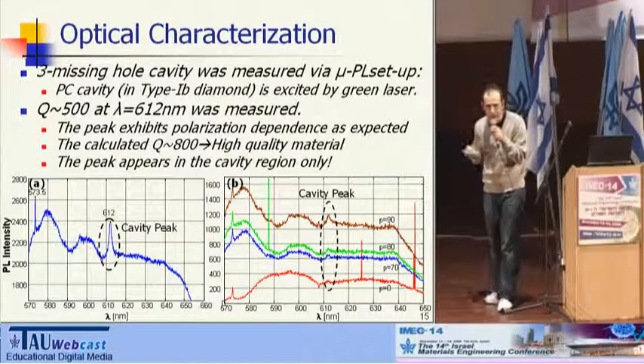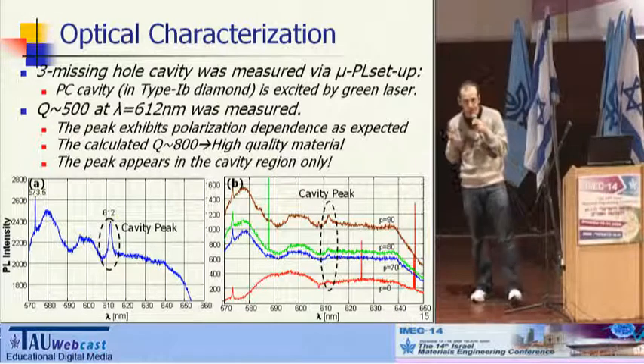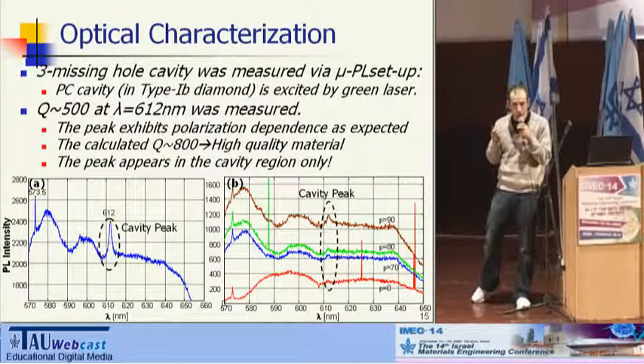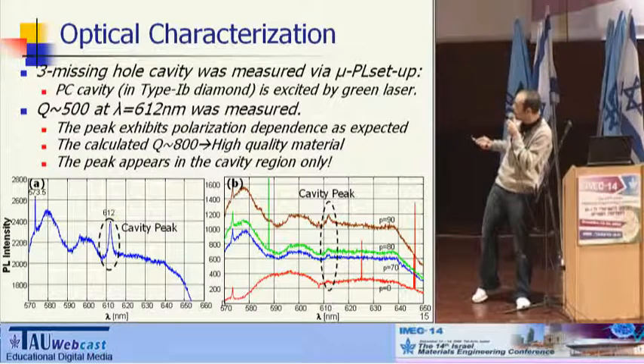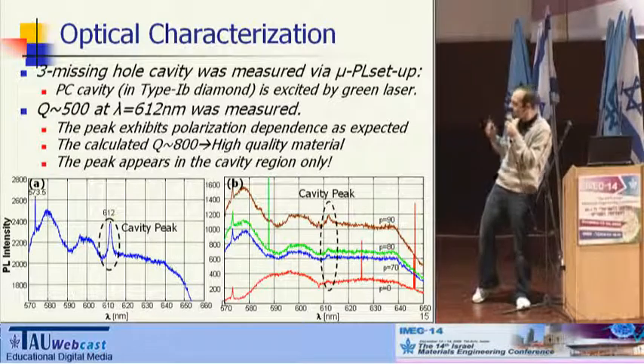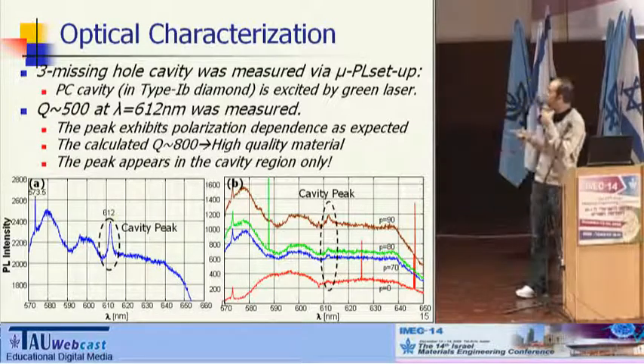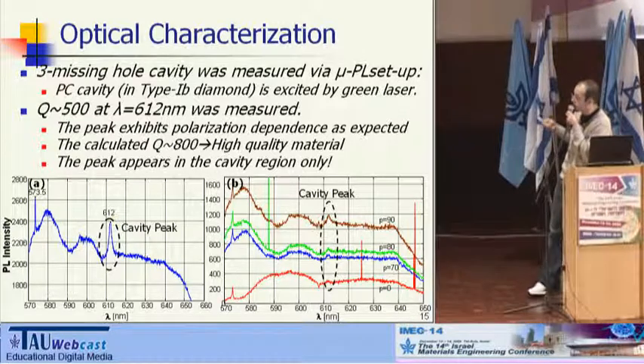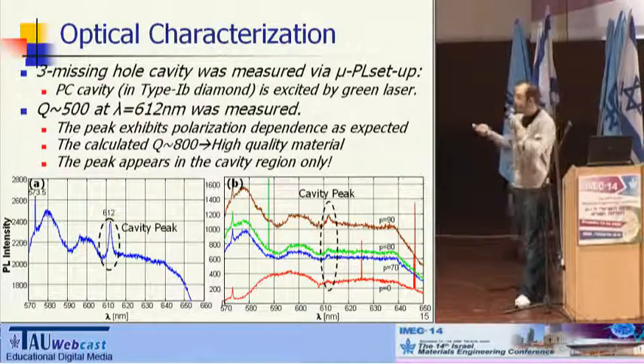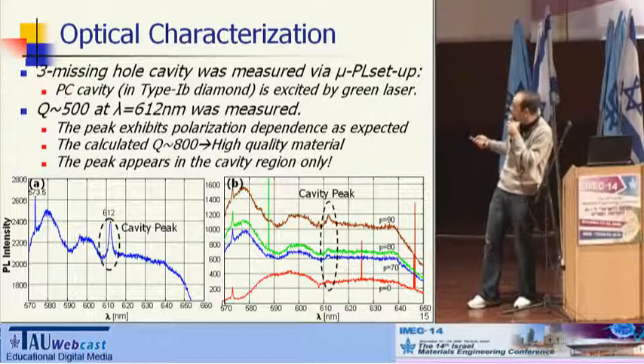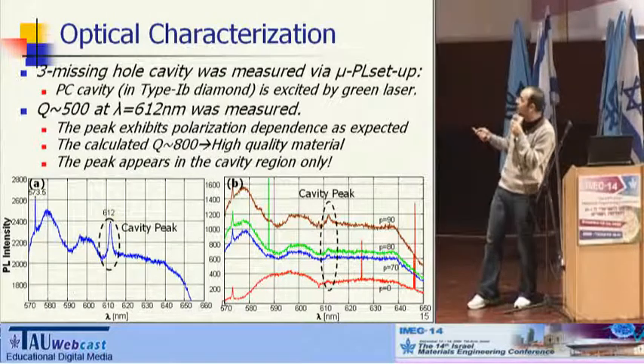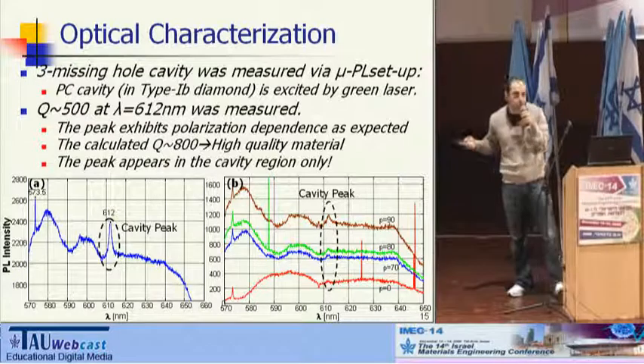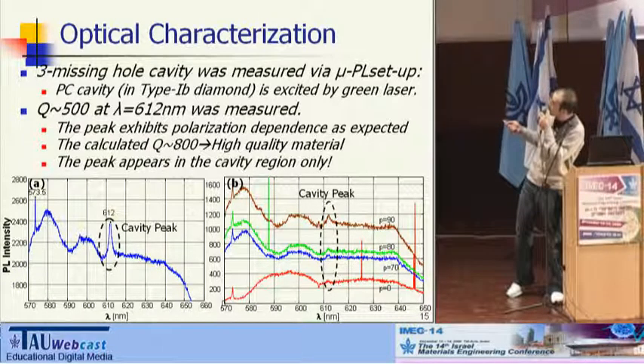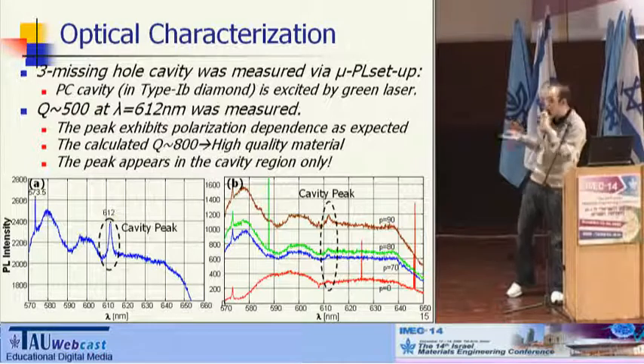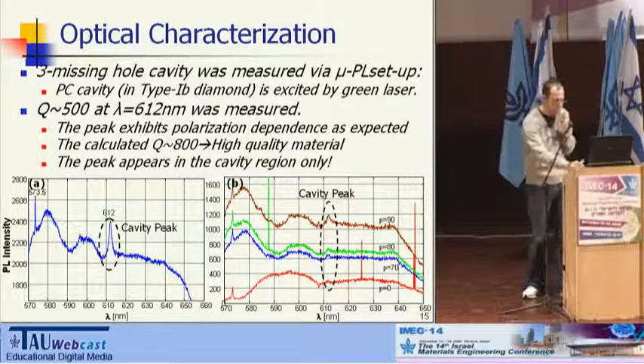As far as we understand, this is the first time a single crystal nanocavity is measured and characterized. This peak appears only in the vicinity of the cavity and disappears outside. When we change the polarization, the peak also disappears. So let me say that this is the first time that this cavity was realized. The quality factor is 500, which compared to our calculated value, which is 800, suggests that we are in a high quality material.